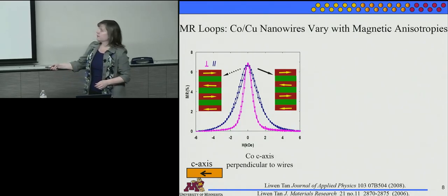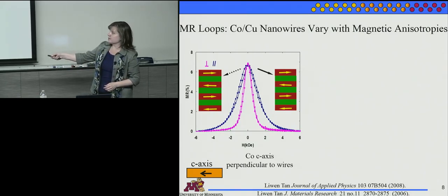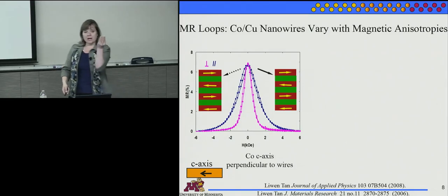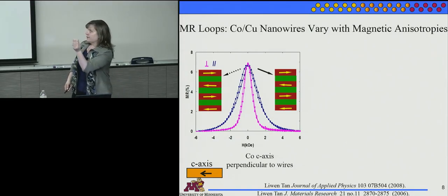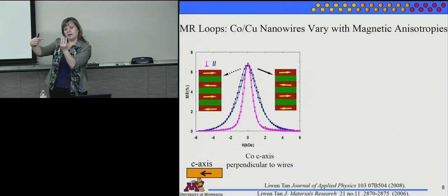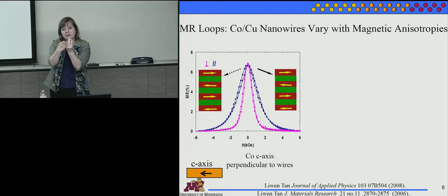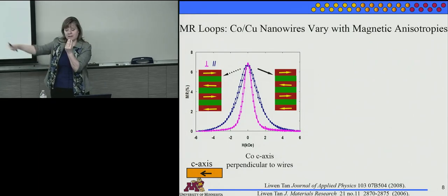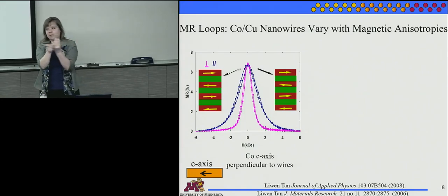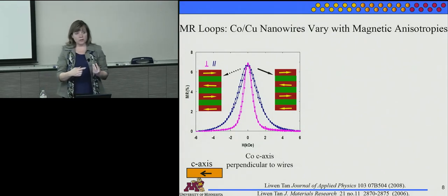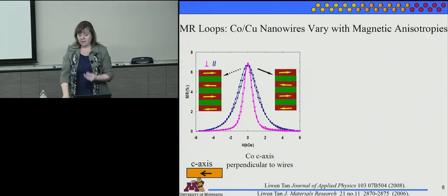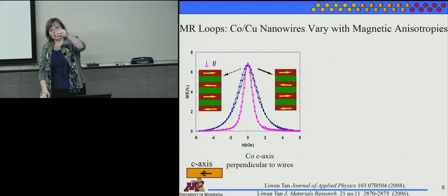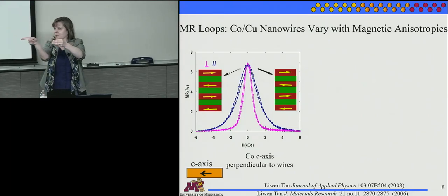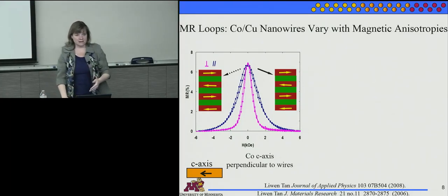So one example of that is if we look at the resistance versus applied field, this is an entire array of nanowires. And if I want to put it in my VSM and apply a field perpendicular, then take away that field and apply it perpendicular, take it away and go negative to positive, perpendicular to the wires, I'll measure a certain resistance change. And if I orient the wires so they're parallel to the field as I apply it and take it away, I'll see another resistance change.